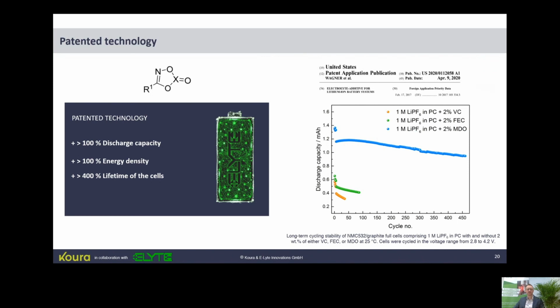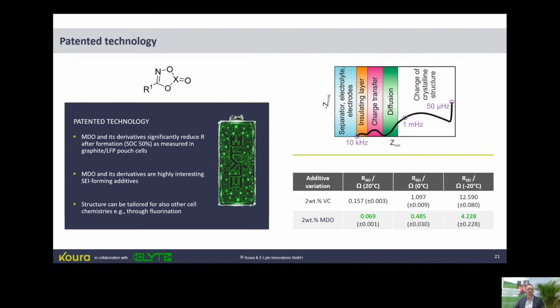So the VC, the FEC is very well known. And what you can easily see is by introducing our molecule, we can increase discharge capacity, energy density, and also lifetime. So based on this work, we did some further work in another cell chemistry.